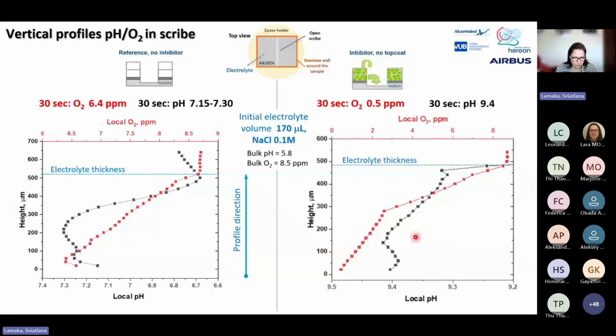And for the inhibitor-containing sample, it was a very different situation. So within 30 seconds, we observed extremely high alkalinization, and this is due to fast inhibitor leaching that hydrolyzes and stabilizes pH at the value above 9.4. And 9.4 is well above the pH stability range of aluminum hydroxide, which is stable in the pH range between 4 and 8.5. So at this pH, we destabilized aluminum hydroxide, and this allowed for very efficient oxygen reduction. And you see the remaining concentration of oxygen at the interface was below 1 ppm. So very efficiently, oxygen was reduced by the active aluminum surface.